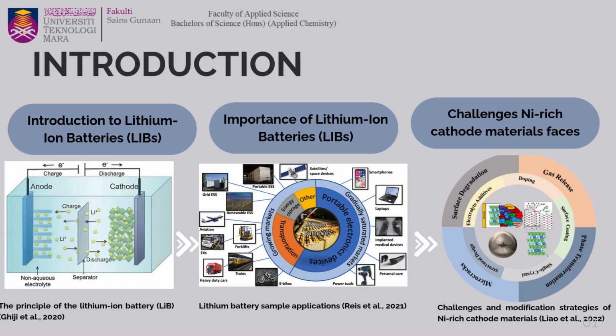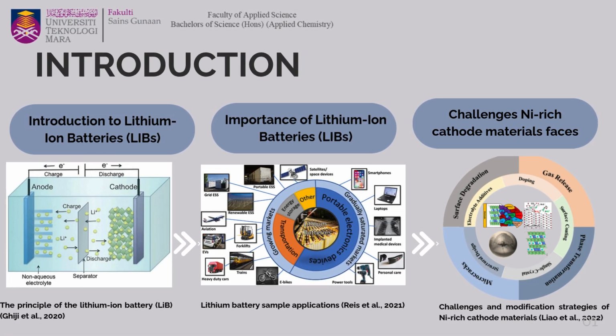So basically, over 60% of total cost of an electric vehicle battery comes from the material used, and a large portion of that cost comes from the cobalt, which is not only expensive but also linked to ethical and environmental concern. Because of this, researchers have developed nickel-rich cathode materials like NMC811 that reduce cobalt content. However, this solution brings a new set of problems, including thermal instability, structural degradation, and capacity fading. So, my research explores how doping NMC with magnesium and titanium can help to overcome this limitation by enhancing its structural and thermal properties.